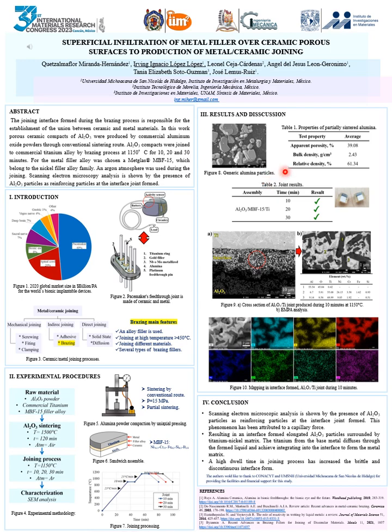Results. The ceramic compacts were made from generic alumina powders with a platelet morphology. These compacts reached a mean relative density of 61%, indicating a high degree of porosity. The joints at the 3 different times were achieved. However, as the bonding time increases, the continuity of the interface bonding decreases. The scanning electron microscope image shows the joint of aluminum oxide and titanium.